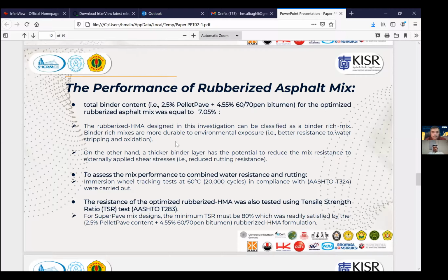In order to assess the mix performance with regard to both water and rutting, we carried out the wheel tracking test at 60 in compliance with AASHTO T324. But unfortunately, the results indicated that it is susceptible to high temperature rutting, as you can see in the